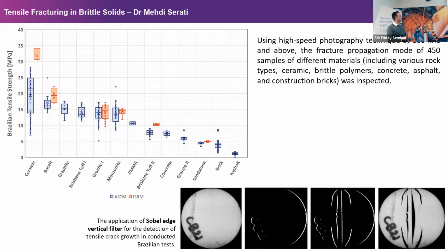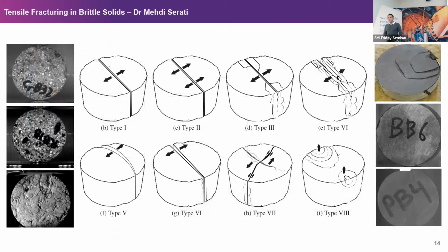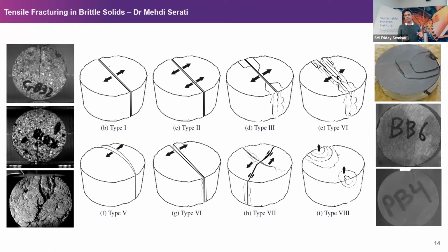We tested ceramic with near 30 MPa of tensile strength, all the way to asphalt, which has less than 2 MPa of tensile strength. In some cases, when we look at the high-speed recording, we need to use a specific filter technique to be able to record the initiation and propagation of the crack. And here is the fun and interesting part. When you test a Brazilian sample of a material, depending on its brittleness index, it's not only one, but you get 8 different types of fracture pattern.